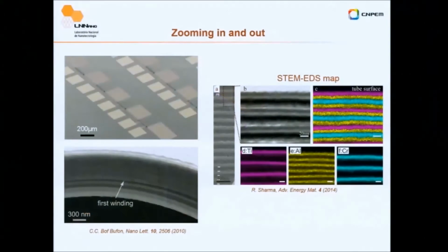So this work evolved a lot in the past years. We can pattern several devices on a chip. Here's a chip, and how the cross-section looks by focused ion milling. You can see very nicely how compact the system is. You can see also some voids in some regions. Here you have a STEM-EDS map of all the elements: titanium, chromium, and the aluminum from the aluminum oxide. This is already a recent paper.